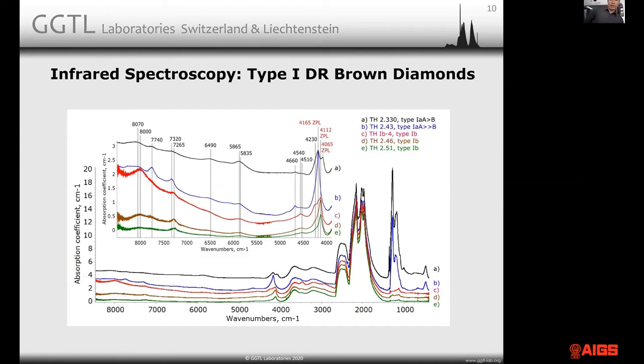Now, another very characteristic thing, now we're getting straight into spectroscopy, is that virtually all type 1, not type 2, DR brown diamonds exhibit strong absorption around 4,000 wave numbers. You can see that in the inset, recorded at room temperature. This defect is known as the amber center, obviously because it's present in brown diamonds mostly. I worked on this diamond center in my work in 2003, and Dr. Laura Massi worked on this center in his PhD thesis, I think a year or 2 later. And so it has been studied quite a bit.